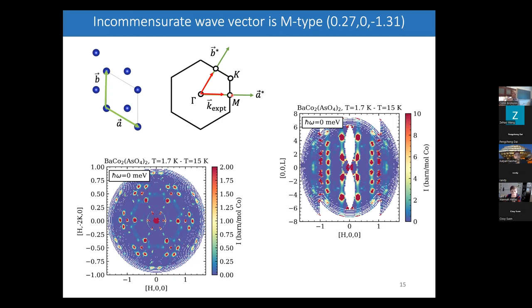However, with the J3 interaction, that's exactly the kind of incommensurate state that we expect to see from the J1, J3 model. So really, to be able to have that kind of magnetic order, you need a J3 interaction to be present. Now, you could say, why don't you just use a Kitaev model with a J3 interaction? And that is also a possibility.